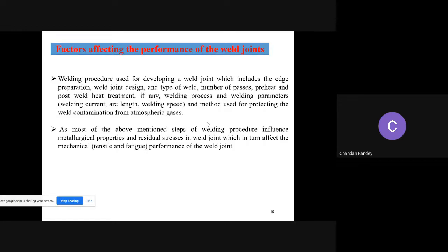After that, preheating and post weld heat treatment. Generally, we perform preheating for some critical materials having martensitic structure, because they create problems during solidification in the heat affected zone, and we get the formation of cracks in that region. We also face the problem of hydrogen induced cracking. So to overcome these things, we perform preheating.